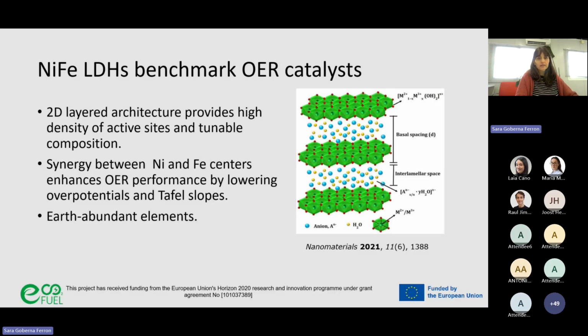Nickel-iron layered double hydroxide structures are widely regarded as a benchmark for the oxygen evolution reaction in alkaline media. This is mainly because they have a 2-dimensional layered structure, which provides a high density of active sites and a tunable composition. A key aspect is the synergy between nickel and iron centers, which is known to enhance the reaction kinetics and reduce overpotentials.